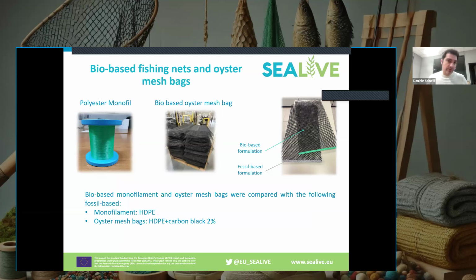Just an overview with the main focus, of course, on fishing nets and oyster mesh bags, for which our organization contributed to the material development in terms of bio-based formulation, spinnability, and material testing in comparison with conventional materials. For example, we used as a benchmark material monofilament in HDPE, and conventional oyster mesh bags that are made with HDPE and carbon black. In both cases, we tried to investigate the use and aging of materials in order to understand what the performances are over time and at end of life, and also test what the end of life is in case of damage and losses in the ocean and sea.